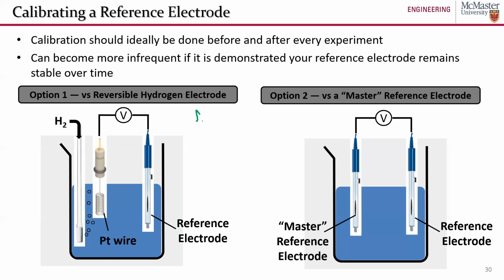I prefer option 1, because you would never know if your master reference electrode drifts, for example, whereas the reversible hydrogen electrode is very well-defined electrochemistry, very easy to make, and it's going to be exactly at 0 volts versus the RHE if you build it and operate it properly. The one quick tip I would give, if you do make your own RHE, is to always make sure to butane torch your platinum wire before you use it. Because that just gets off any junk, any organics, any species that may have built up on the surface of that platinum wire and could impact your measurement.